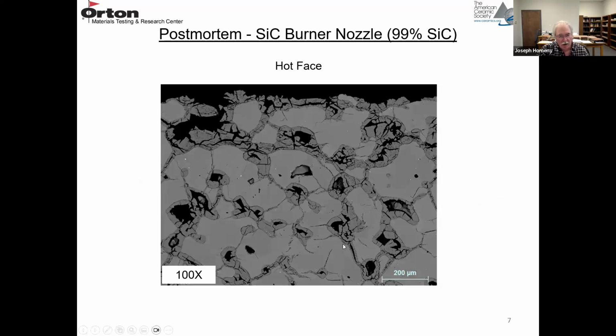So at a little higher magnification, you can see the individual crystals of silicon carbide. They're in the lighter gray. The darker gray that's highly microcracked is the oxidized material. So you can see the surface is oxidized and oxygen diffuses through the structure, attacks the silicon carbide at the pores, and it moves along the grain boundaries.